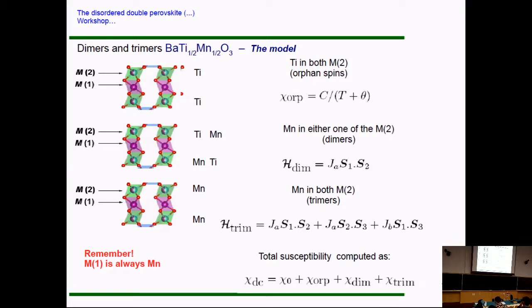So since all manganese cations sit in trimers, if you work through the possible occupations, you can have either, let's say, an isolated manganese spin, which we can call an orphan. You can have a dimer, meaning this kind of occupation here, which you can model like that. And you can have a trimer like this one, right, which we can model like that. So if you try to describe the susceptibility in this way, this is more or less what you would get. These are the possible contributions, and we try to describe the magnetism at high temperature, right?